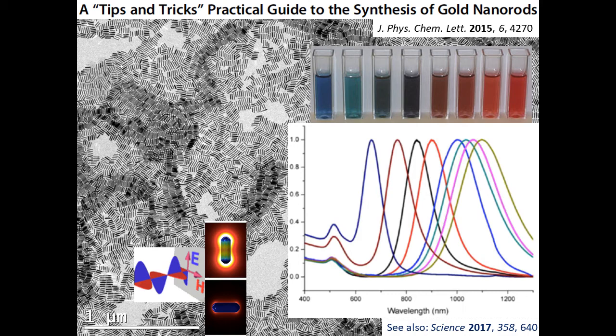Now, the state of the art for gold nanorods is something like this. So you can make really large amounts of material in a short synthetic process with a very high quality. Let's say that the standard monodispersity nowadays is around 10% in terms of ratio between the length and the width, which is what in the end defines the optical response. If you go to this paper, you will find that by manipulating pre-made colloids, you can go down to 2% monodispersity, so actually to very narrow absorption bands.